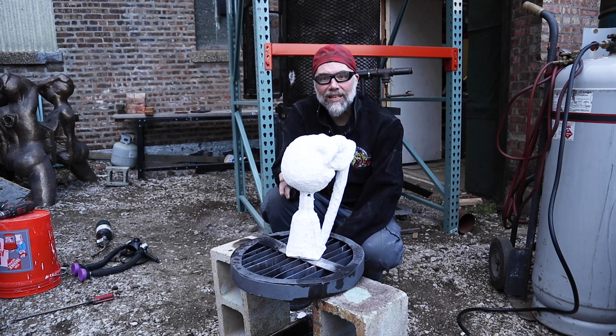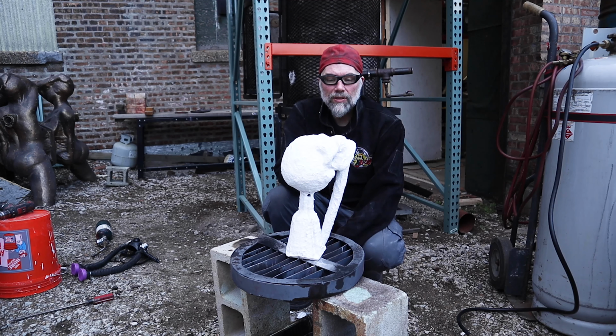For every shortcut, there's a price. And the price on this technique is that it's a little slower, you eat up a good bit more gas, and ultimately, like I said, probably easily 9 out of 10 times, you're going to crack your shell. But typically the cracks I do get with this type of burnout are super tight and subtle, to a point where yes, they need to be patched before the pour, but they won't necessarily create defects in my metal in such a drastic way that needs a lot of patchwork or a lot of grinding and chasing work in the metal later on.